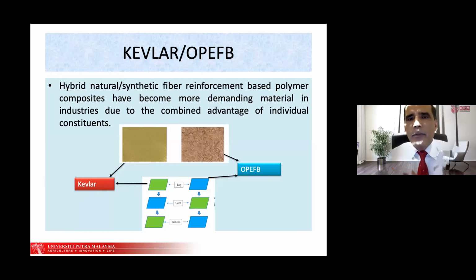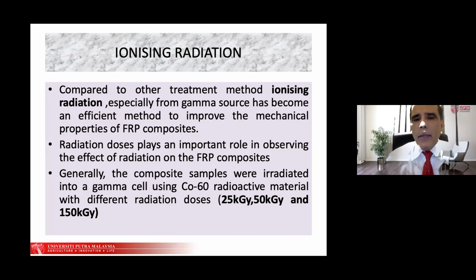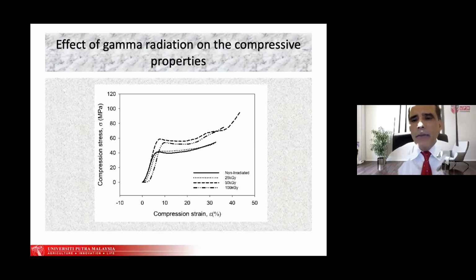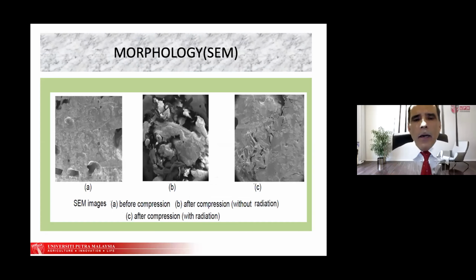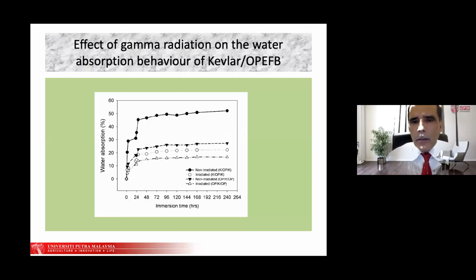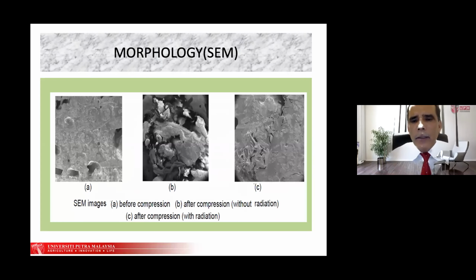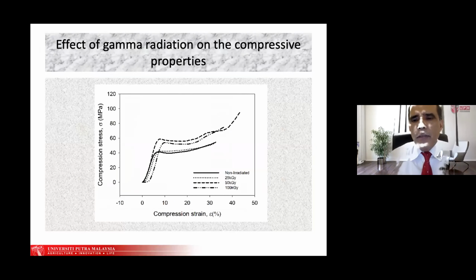There is one student working at the Nuclear Malaysia Agency, so she helped us, she had access to the Nuclear Malaysia Agency. So we irradiated the samples in the gamma cells using different radiation doses. And we find that the water absorption improved, and the interaction between the fiber and matrix also improved after irradiating the composite, and compression strength also improved. For example, 50 and 100 show better results compared to the non-irradiated and the 25.